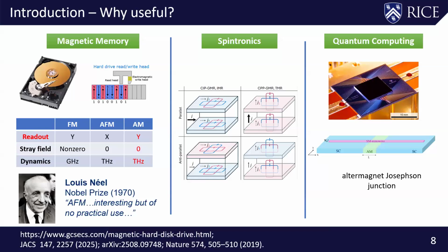When Néel discovered his famous antiferromagnetic order, he made a statement that it was interesting, but he was not sure what it would actually be used for. But nowadays, all hard drives use spintronics, and one of the major problems is the stray field. A simple ferromagnet, because of the dipolar interaction, would exhibit a fairly large stray field, but an antiferromagnet would not. So the question is whether an altermagnet would combine both: giving rise to ferromagnetic properties, yet not having a very large stray field.